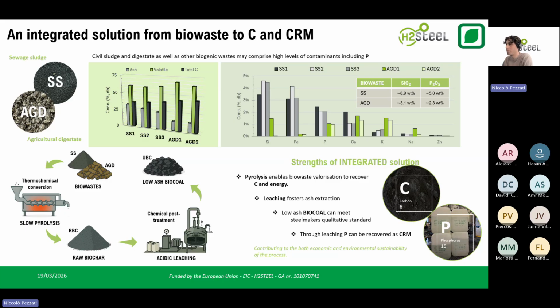Also, one fundamental aspect of all of this is the phosphorus content in these biowastes, because apart from recovering carbon to produce the fossil coal substitute, if we are able to recover at the same time phosphorus, which is included in the critical raw material list by the European Commission, combining these two aspects together, it is possible to increase the added value of the process, delivering carbonaceous material and at the same time allowing to recover a strategic element with relevant markets.